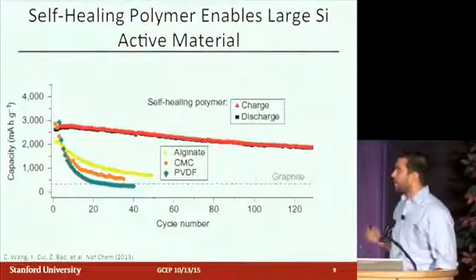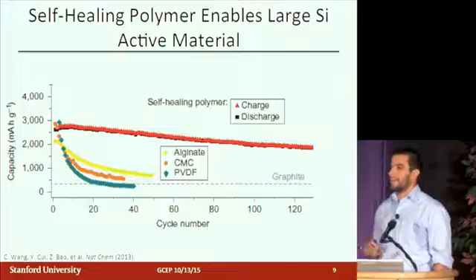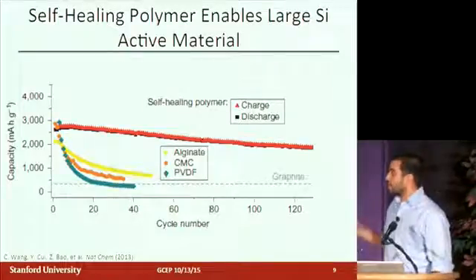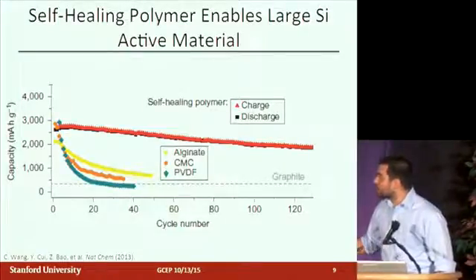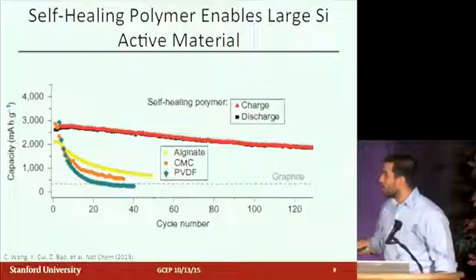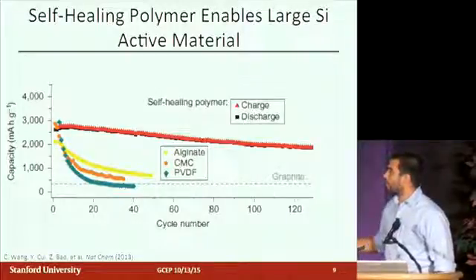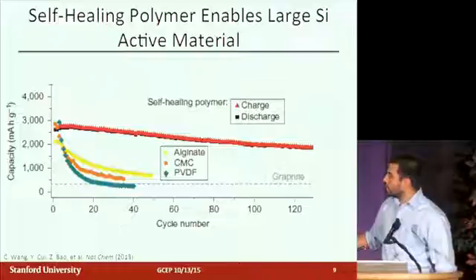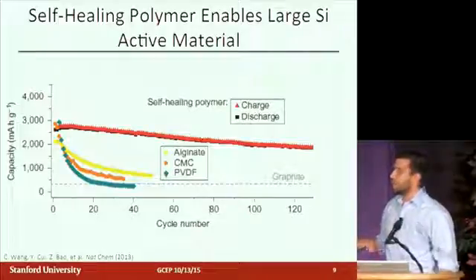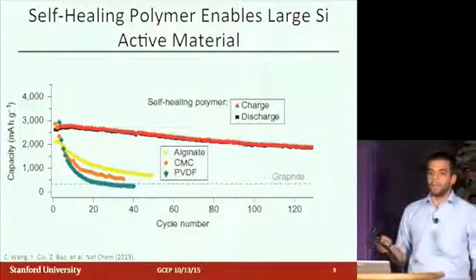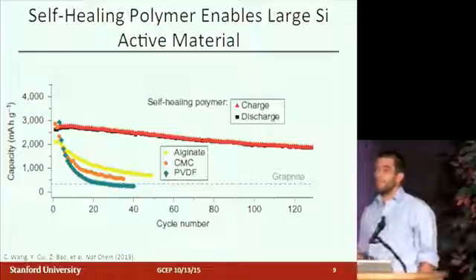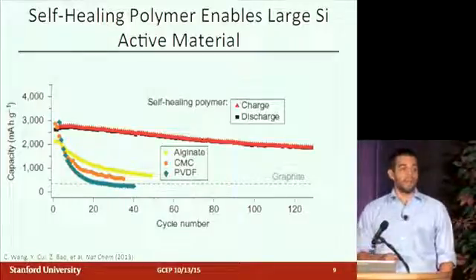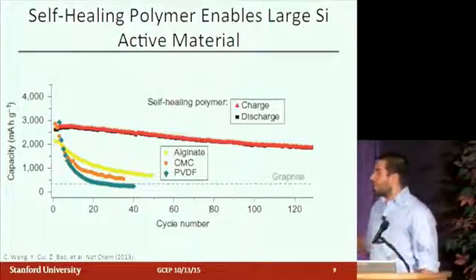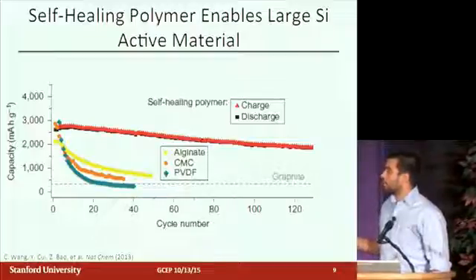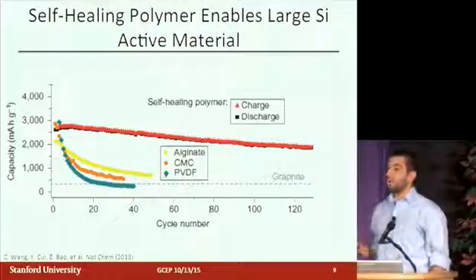And now really the important piece of data with the battery cycling is just the cycle life. So you can see this is charge stored and then cycle on the bottom, so how many times we've charged and discharged it. And comparing it, you can see alginate and CMC are two of the carbohydrate polymers that I was talking about before, and then PVDF is a binder that's used in graphite electrodes commercially. And we have much, much better cycling life than any of these with large silicon particles.